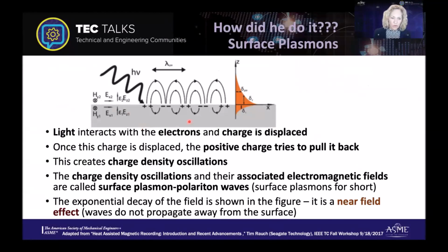So this is one of those small scale effects, and it's a surface effect. If we have our little silver film here and light interacts with that film, it interacts with the electrons and the charge is displaced. When the charge is displaced, the positive charge actually tries to pull it back and you start to get charge density oscillations. The charge density oscillations and their associated electromagnetic field due to the charge movement are called surface plasmon polariton waves, or we'll just call them surface plasmons for short.